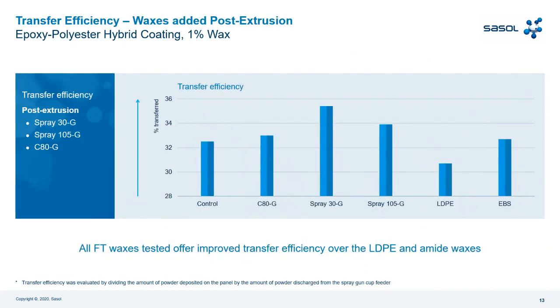Then for transfer efficiency, you need to look at the control, and the best value is the highest. So in this case, for transfer efficiency, Sasol wax Spray 30G achieved the best results. It's a micronized wax, 6 micron. Then following are Spray 105G and Sasol wax C80G.